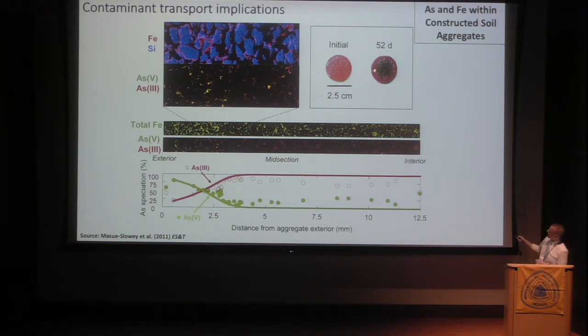And you can see over time, now the cross-section through this, there is still this oxidized rim and then a more reduced zone in the interior, using microzones to track the production of arsenic 3 and then the loss of arsenic 5 across time and across space. These oxidized rinds on the exterior of these artificial aggregates serve as a barrier for arsenic and also iron 2 to diffuse out, but do result in the buildup of arsenic within these regions. And changing geochemical conditions could easily result in a pulse of these materials out, again highlighting the importance of microzones within this.